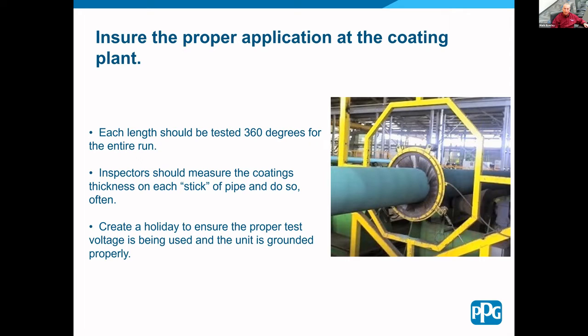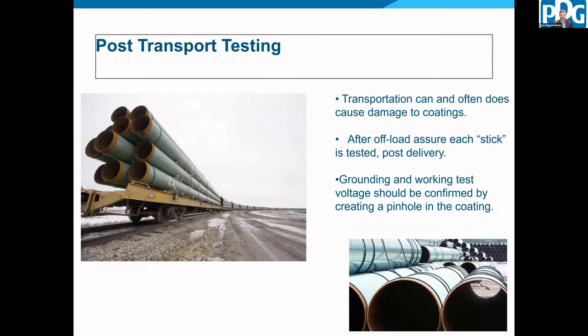And so you want to move your holiday probe over a little bit from the hole, twice the distance of the coating thickness, and be sure you still get a spark. Basically, is what you were saying earlier, right? That's correct. So what we do is we actually approach the holiday so the arc jumps. Once it's in there, we then retract or move back away from the holiday to make sure that we've got that twice distance as the coating is thick.